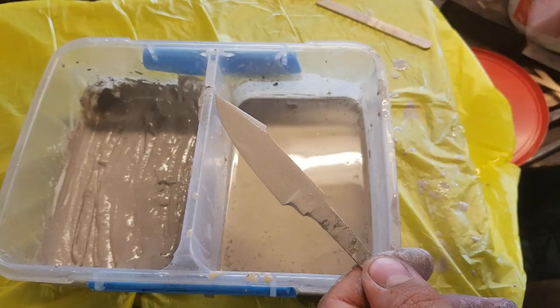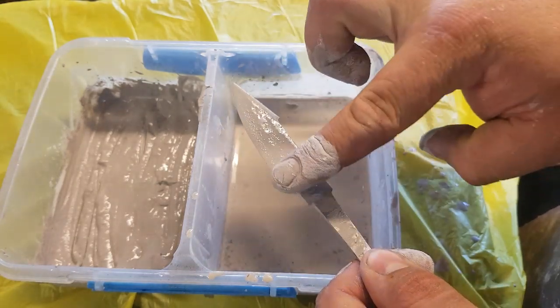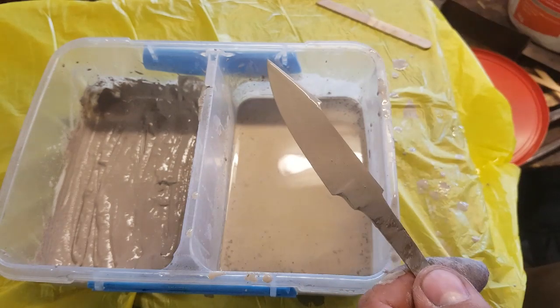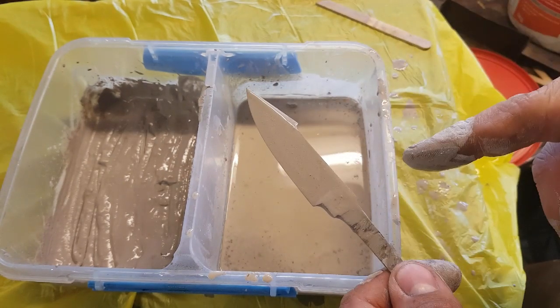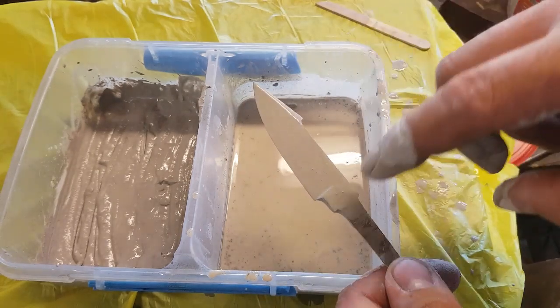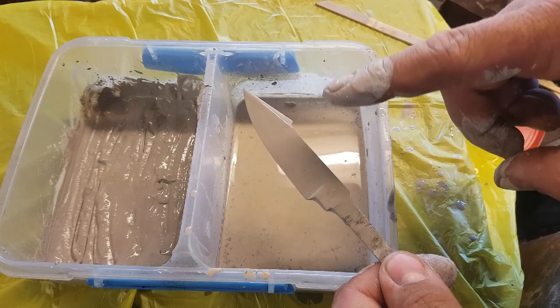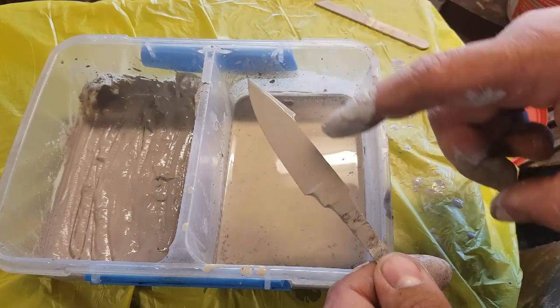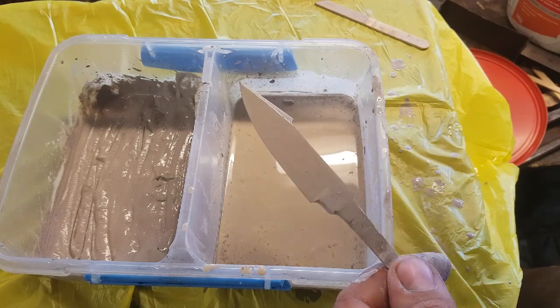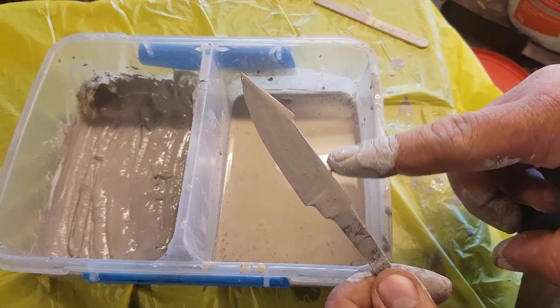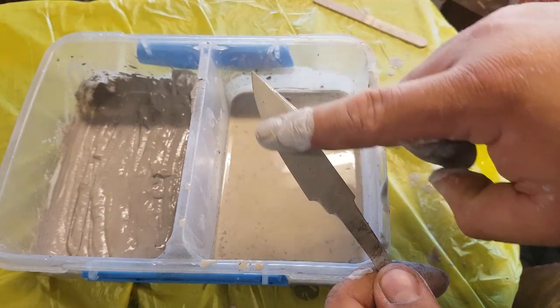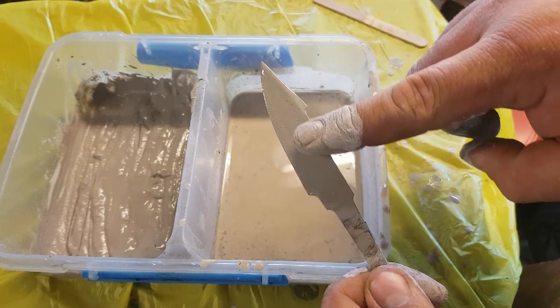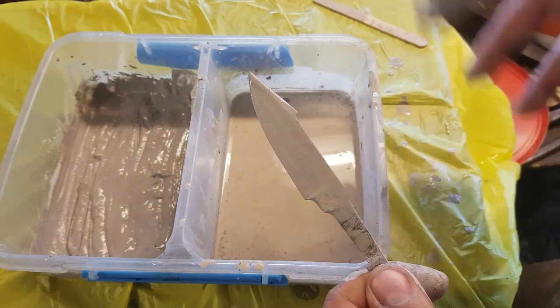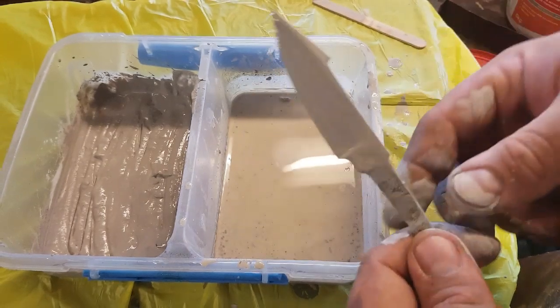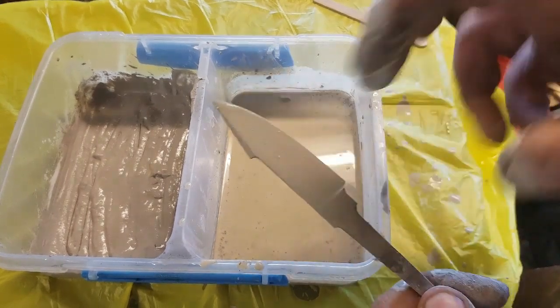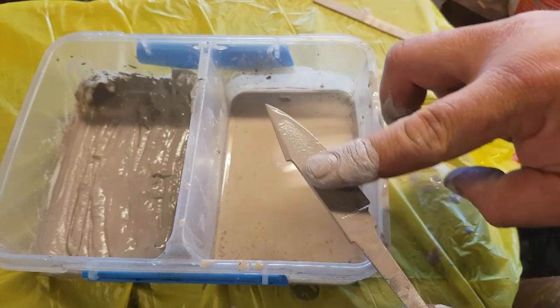And what this is doing is A, protecting the steel from oxidization during the heat treat, because the clay will protect the steel. It also increases the surface area, because there's all these little granules in it, which means that the areas that are not covered by the large, thick amounts of clay will actually cool faster than if they were just bare. And this is actually a method that the Japanese use to heat treat kitchen knives and stuff, is that they will actually apply a thin layer of clay to all of their blades. They won't apply a Hamon line of clay, but they will apply a thin layer like this to all of their blades to increase that surface area to speed up the quench to get an even higher hardness out of their steels.